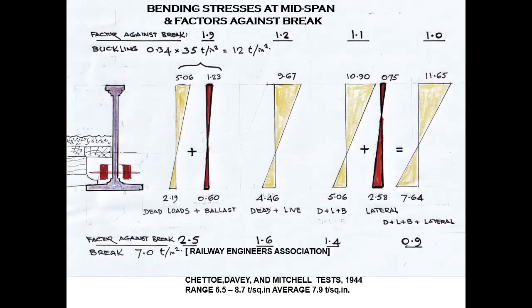So what are the stresses in the girder? This shows the bending stresses at mid-span, and it also shows the factor against break, which of course should be something like 3 or 4. But you can see under dead loads plus ballast, top flange is on 1.9, but as we add the live load down to 1.2, as we add the ballast 1.1, and then with the lateral effects we're down to 1.0, we've actually collapsed. What is the compressive stress based on? It's based on a buckling factor I've used of 0.34, which I'll explain shortly, times the ultimate stress in compression of cast iron of 35.